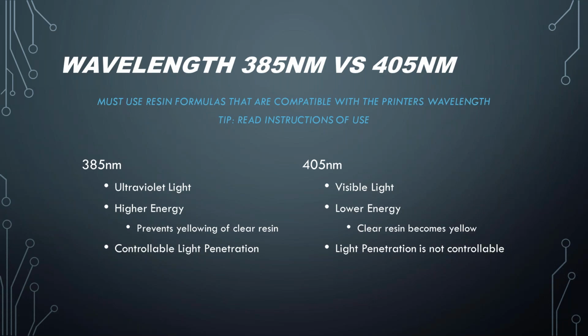The 405 is a visible light. It is lower energy, but because it is a lower energy light, you can't actually control that light penetration, the depth of cure. I follow different dental printer Facebook groups, and I always get a kick out of people that are using a 385 resin in a 405 printer, and they'll never have an accurate object, or they'll say, oh, look, it cured into the supports. I was printing a surgical guide, and now my object is cured beyond the supports, and it looks more like a blob. The reason why is because they're using a 405 light and a 385 resin. Also, with the 405 nanometer resins, they're going to have to place pigments in it to prevent the depth of cure from being too far. So you'll never actually receive a true clear resin with a 405 nanometer printer. And if you do try to print a clear resin, you have a high chance of it yellowing immediately after printing.